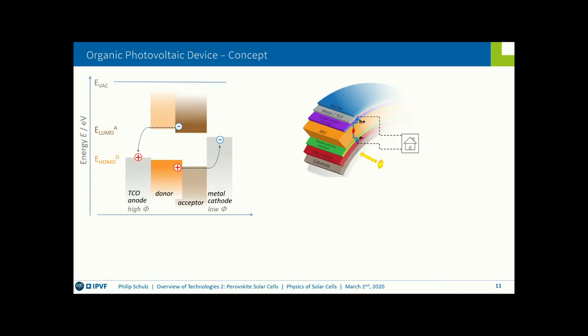And here we see a significant drop in VOC, but as has been said earlier, the first thing that takes a hit is the fill factor. Now it becomes even more prevalent if you have these pathways not disconnected by an only hole or an only electron transporting material, but here in the realistic solar cell you have a bulk heterojunction, which means you actually mix your donor and your acceptor films in order to maximize your donor acceptor interface area.